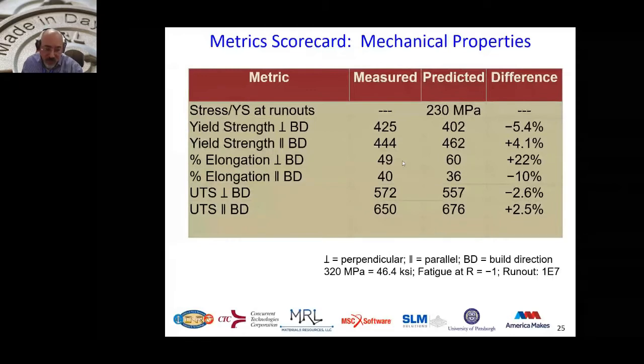When we came to elongation percent, and this has been the Wild West everywhere, it is just due to the current parameters requiring a lot of information to predict the damage, which is related to the elongation percent. This is where we were a little bit outside of the range, but knowing this material is not expected to be plastically deformed. The approach that we are sharing with you doesn't only apply to SLM. We applied the same approach in other machines. We applied it to 3D Systems, and we are in the process of applying it to EOS machines, and we also have a plan to apply it on Arcam machines.